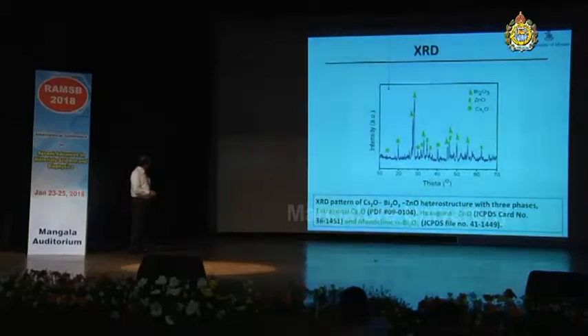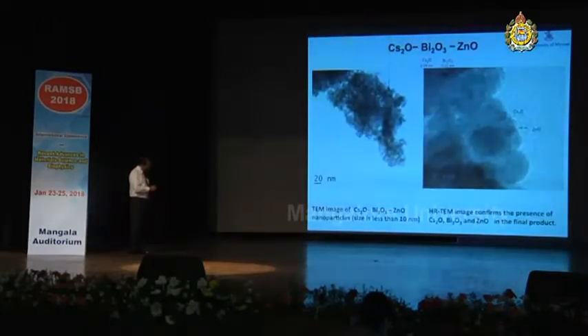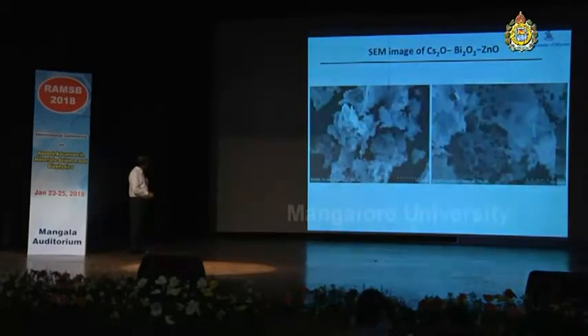But look at this. These are the X-ray diffraction patterns showing the presence of all the three phases, as shown here: tetragonal phase, hexagonal zinc oxide, and alpha bismuth oxide in monoclinic phase. And you can observe very clearly the high resolution TEM image, and this is a TEM image of the same compound which you saw here in this graph.